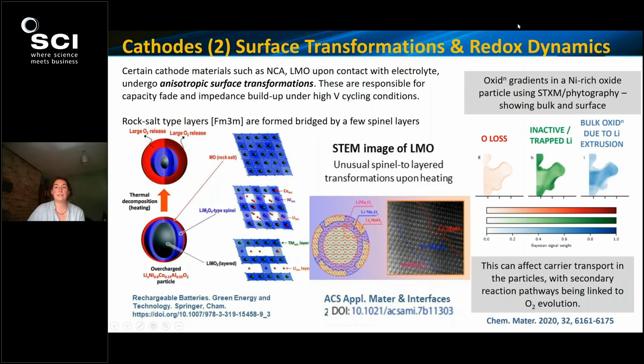And also we can get different gradients of oxidation states in single particles. So this schematic on the right is showing single nickel-rich oxide particles that were analysed and characterised using ptychography. And so in the red image here, you can see gradients of oxygen loss, or in the middle, areas where there is inactive or trapped lithium. And the image on the right is showing bulk oxidation states due to lithium extrusion.